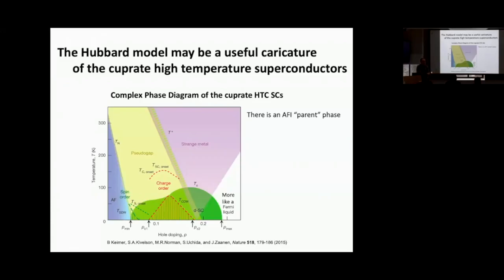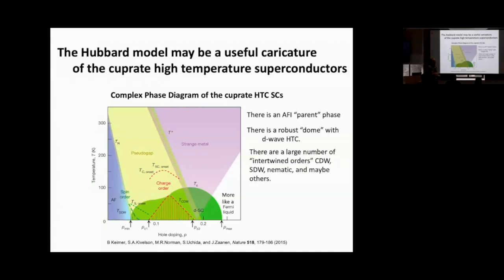So what are some of the salient things that one would like to understand that this phase diagram presents us with? Well, one is there's the antiferromagnetic insulating parent phase. There's a robust dome of D-wave superconductivity with high transition temperatures. There's a large number of other ordered phases that have similar energy and temperature scales as the superconductivity itself. This is something we've referred to as intertwined orders.